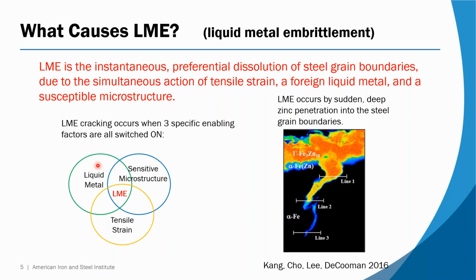So if you have all 3 of these things simultaneously, you have this common area in the center where you may get LME. Here's a picture somebody made of an LME crack, and you can see the zinc running into the material. But it is something that happens very, very quickly when you have the correct magic conditions, if they're all switched on.